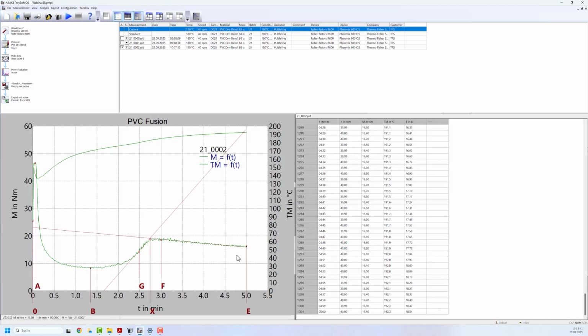After a while we do see that the torque gets constant, so we come into kind of a steady state, and this torque now shows the relative viscosity of our compound. After the test time has finished, the mixer will stop and will now automatically calculate the points of interest at our curve. So we can see here it looked for the beginning of our trial, looked for the first maximum, well, the minimum. We see here the point of inflection in the increase of torque.